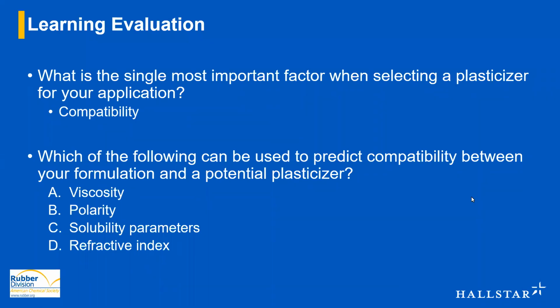So yes, what we're mostly looking at here is polarity, number one. That's kind of the quickest and easiest way to predict compatibility, and solubility parameters. Those are some of the biggest tools. Viscosity is more when you're looking at mixing. Sometimes if your viscosity is too high, or there's an adjustment between the plasticizer and the polymer, it can have more to do with the initial compounding and getting the two materials to come together. But typically viscosity doesn't have too much of an effect on the overall compatibility between the two.